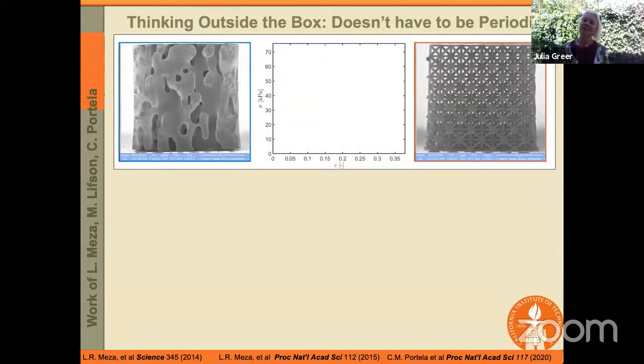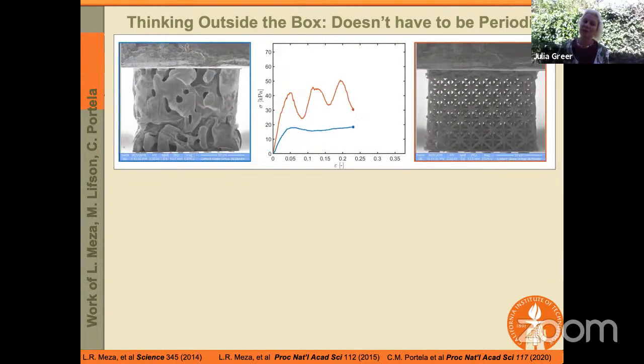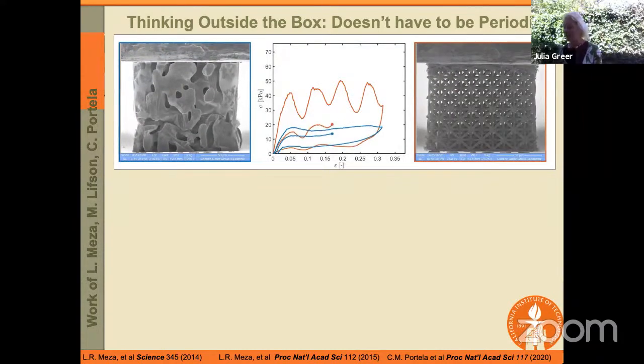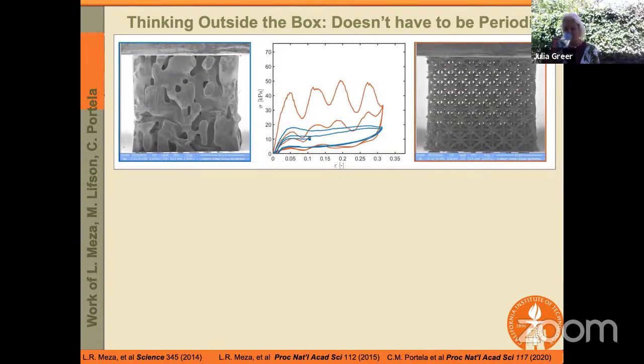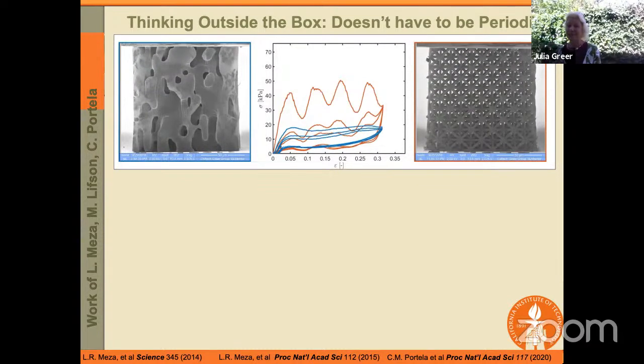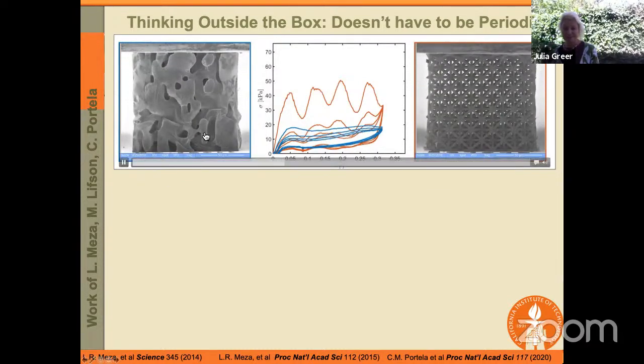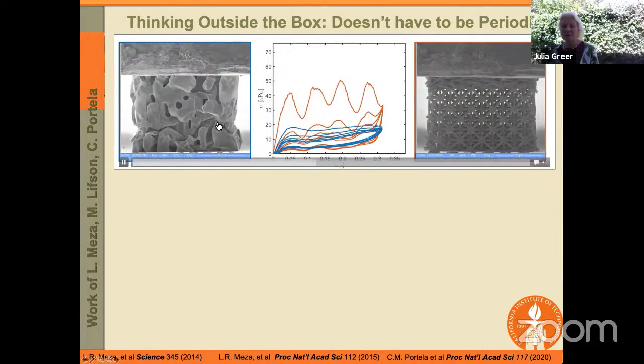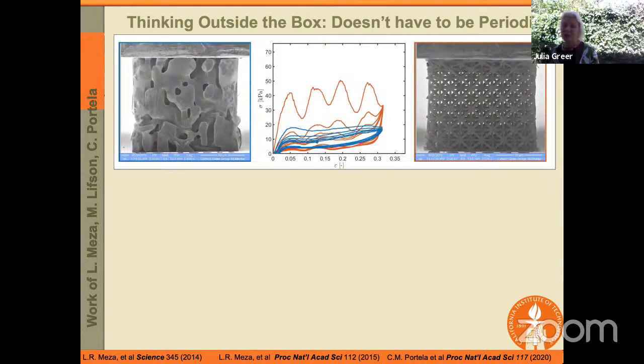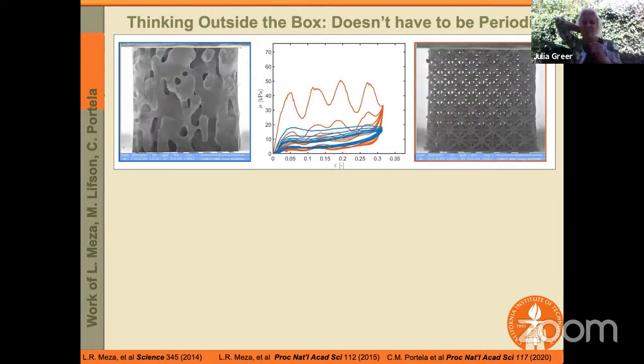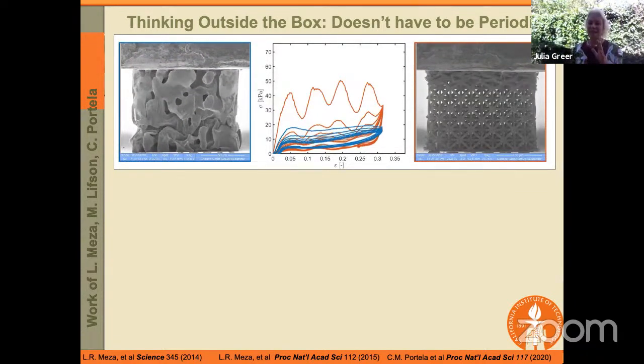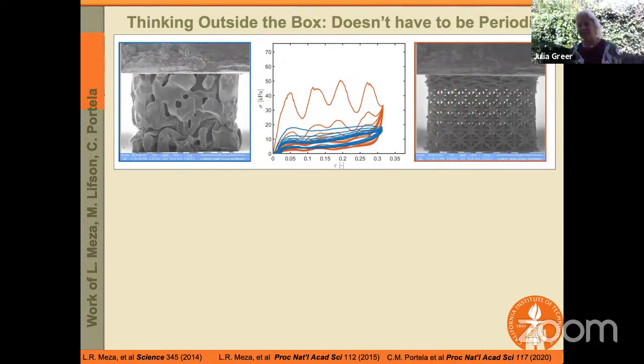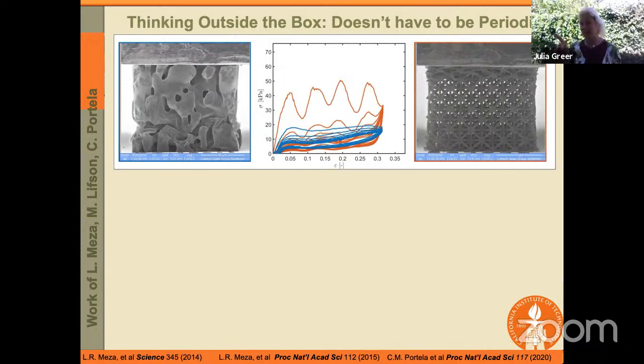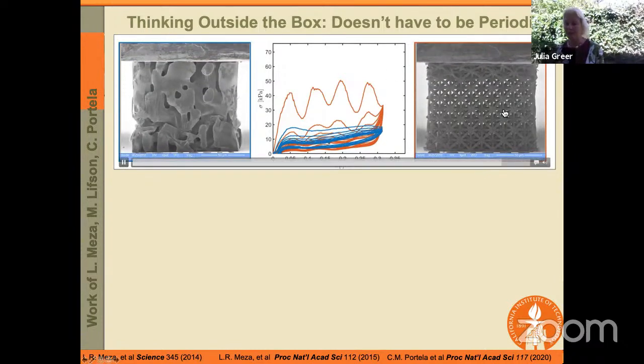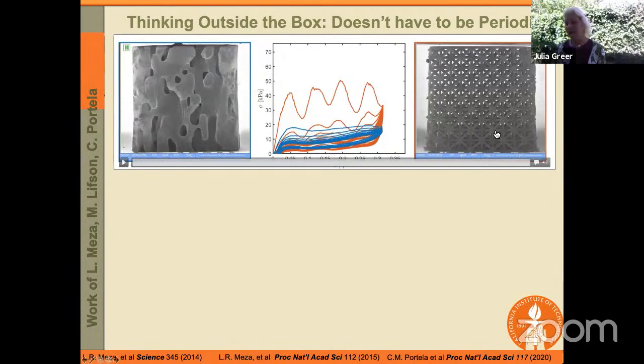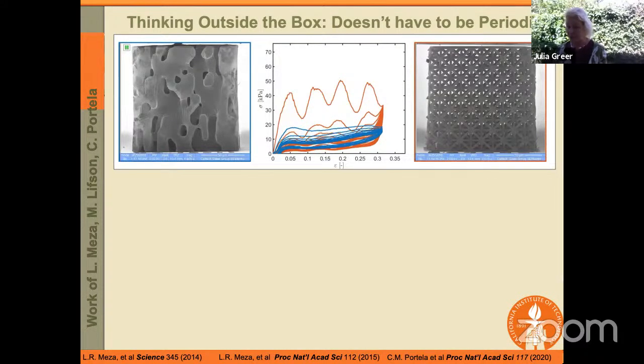So since that time, what we've learned is that this effect of recoverability and mechanical resilience prevails in a variety of different, much more complex architectures. You can see that, for example, they don't have to be periodic. So what you see here is a so-called bicontinuous or nano-labyrinthine architecture. So it's made out entirely of a curved surface. There are no beams. And so you can see that the stress state that develops, of course, is very complex. And yet every time it recovers, and you can see this happening on the right as well with the periodic architecture, where the bottom part is not even subjected to the compression.